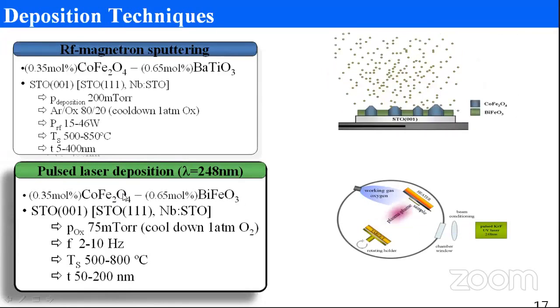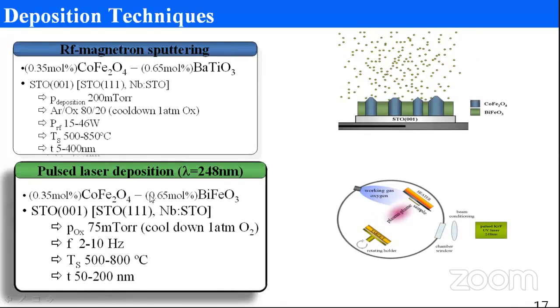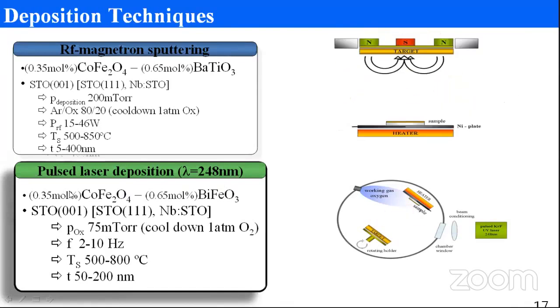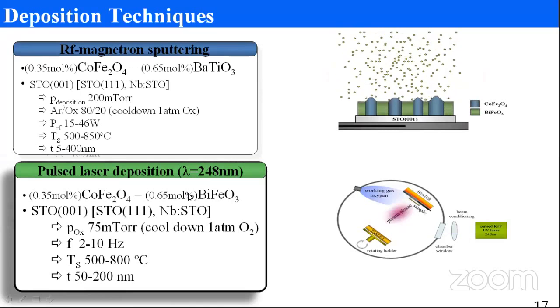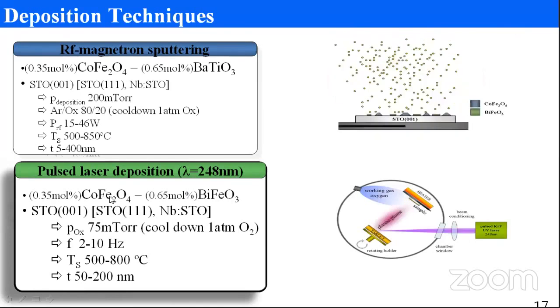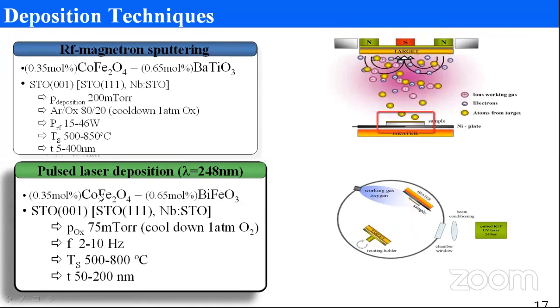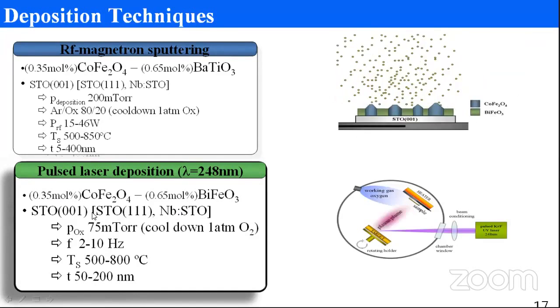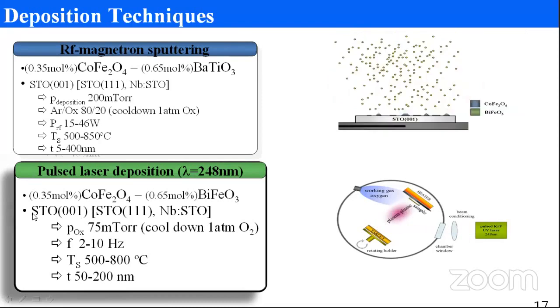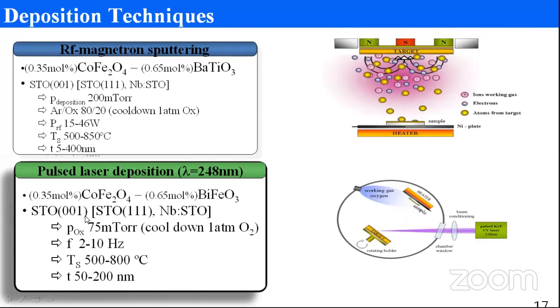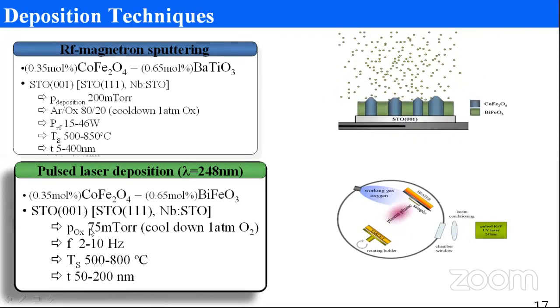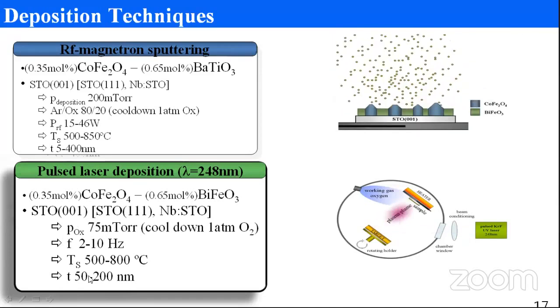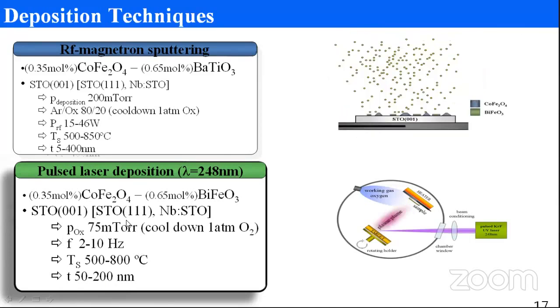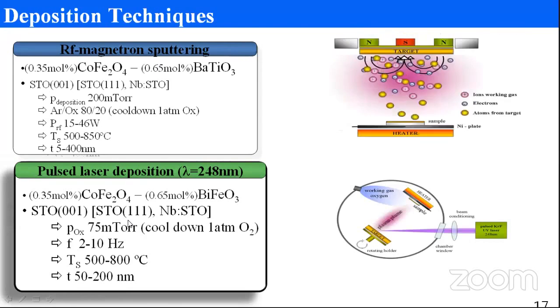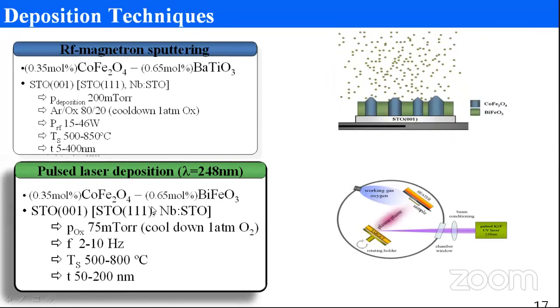We also tried other compositions. In this presentation, I'm not going to present my results on different compositions. Whatever results I'm showing are only on this composition. I'm going to stick with the strontium titanate substrate, one substrate, and these are the growth parameters which we maintained for an optimal epitaxial growth of these nanocomposites.